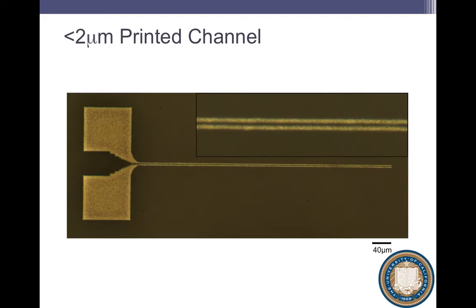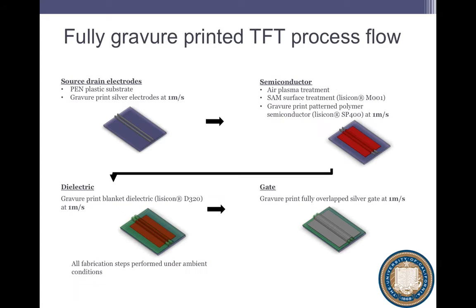But for you, you could imagine printing resist at high speeds and then patterning your thin films. So if you ever hit an application where someone says, well, your sputtering is cheap, but I have no way to pattern, you've got a way to say, hey, you ought to consider print-based patterning. It'll still give you the high quality of your sputtered films or your evaporated films, but now it gives you patterning that is much more scalable. So we use that then to print devices.